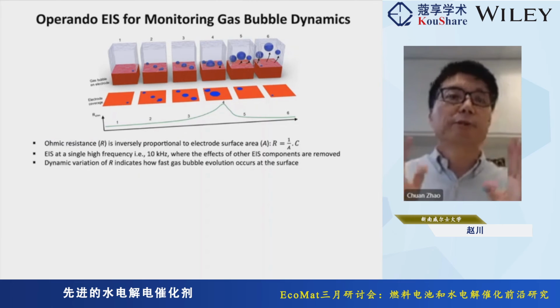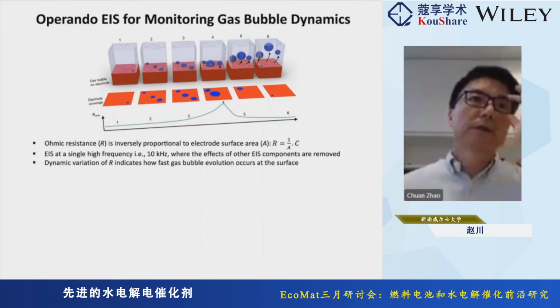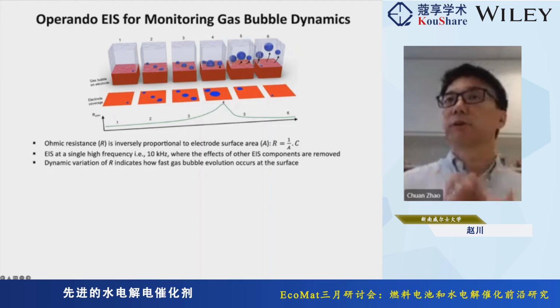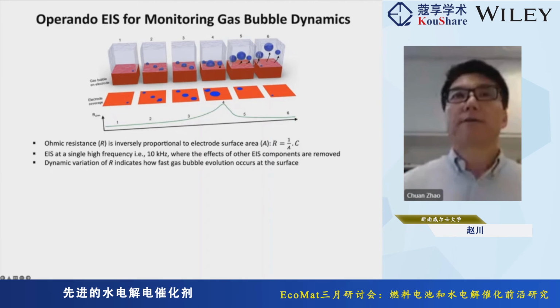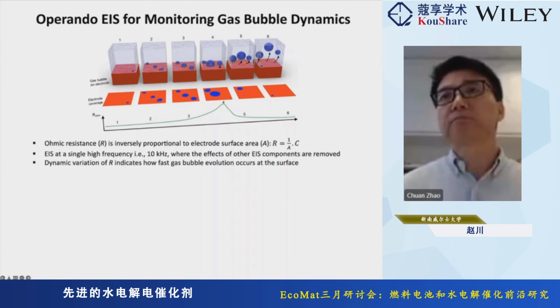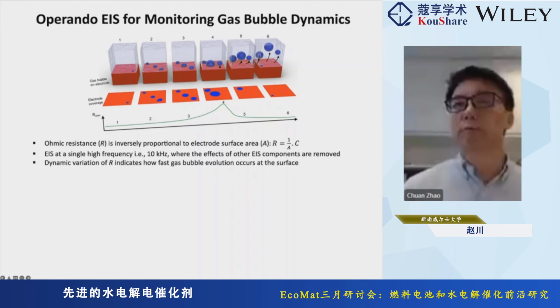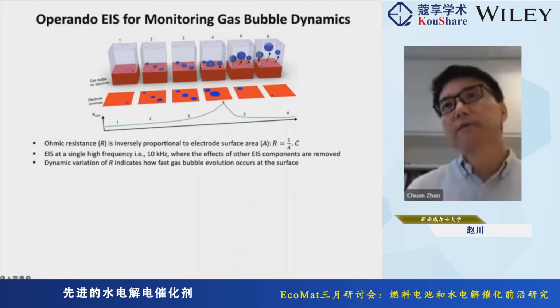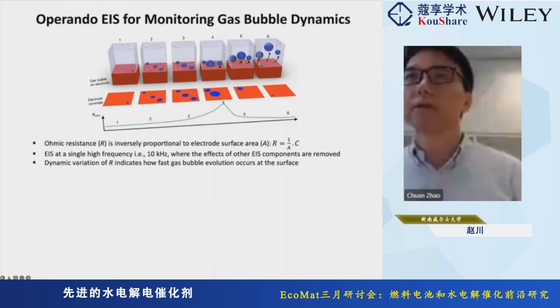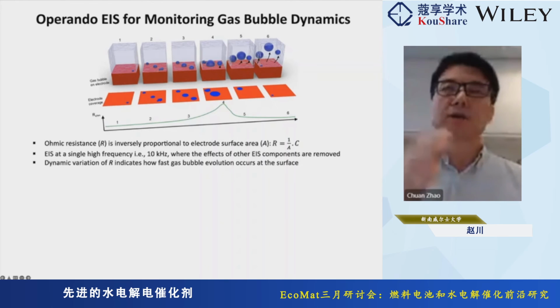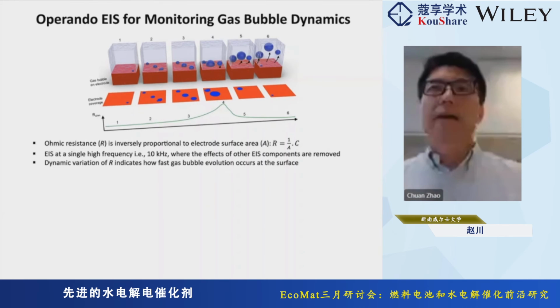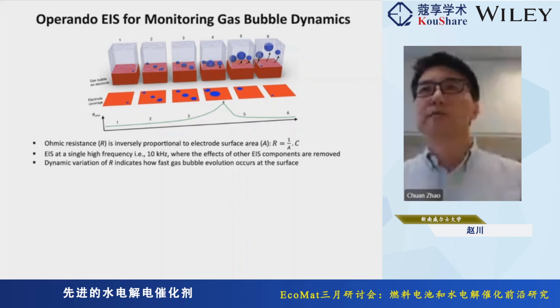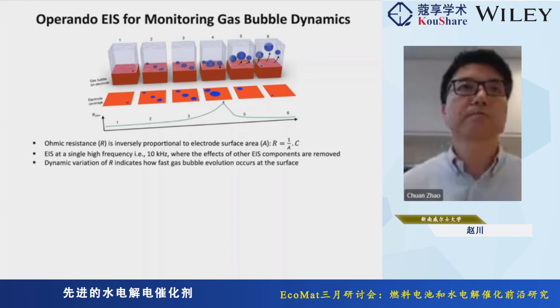The fundamental principle is very simple. We know the ohmic resistance of the electrode surface is inversely proportional to the electrode surface area, right? So when you have a bigger bubble on the electrode surface blocking the surface area, we have a higher resistance. It can simply be described by this equation, where C represents a coefficient for your cell, which can include the electrolyte used, the electrode material, geometry, the distance between electrodes, and all the other factors.